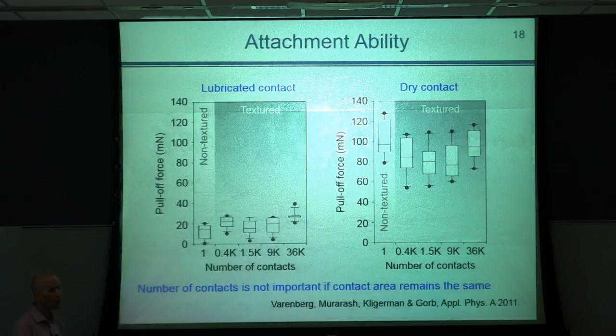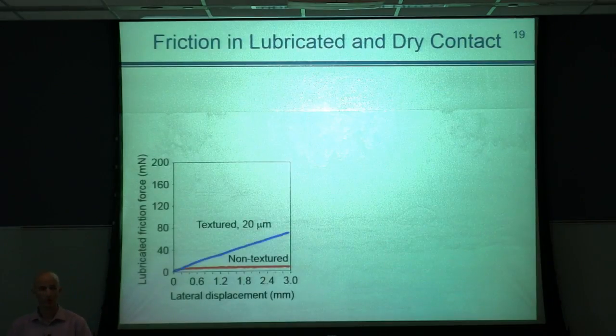So when we have more hexagons on the surface, while the contact area was the same in both cases. This is lubricated contact, this is dry contact. You can clearly see that despite the number of the surface projections increasing by about 2 orders of magnitude, we have the same pull-off forces in both dry and lubricated contact, which means that the contact splitting principle doesn't work here. So we turned our attention to the friction hypothesis, and we tested the structures in both lubricated and dry